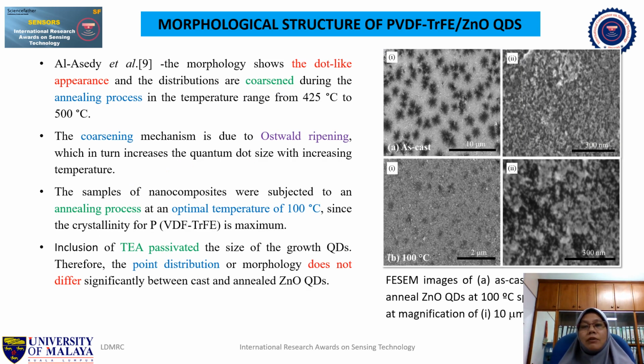Morphology structure of PVDF-TrFE zinc oxide quantum dot is also investigated by using FESEM. So the figure here indicates the structure of zinc oxide quantum dots. This is before annealing and this is after annealing at 2 magnification. So from this picture, the annealing temperature used is 100 degrees Celsius.